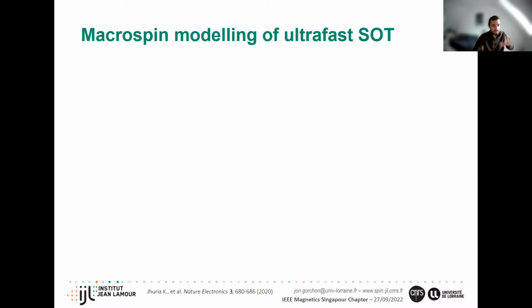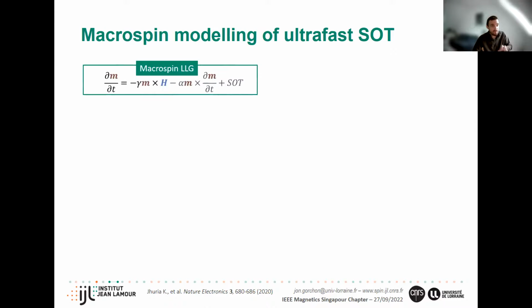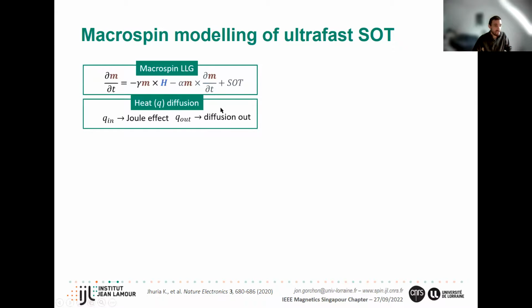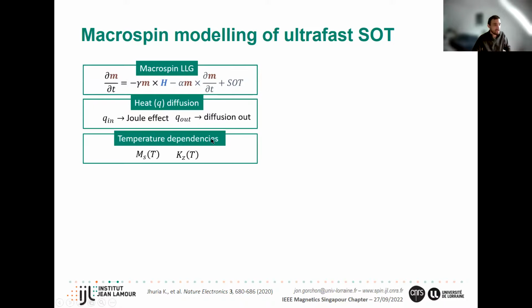So we added all of these ingredients into a very simple macrospin model. So we have the macrospin model plus the SOT torques. We added a very simple heat diffusion model. So we just have Joule heating that brings heat into the system and some diffusion that goes out of the system. And so we can have the temperatures change in the system. M and K are temperature dependent.